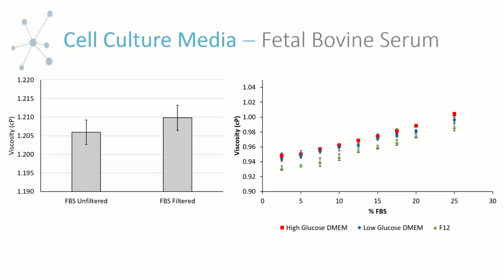And then we wanted to see how the combination of FBS and different mammalian medias, how does FBS influence their viscosity, since FBS is a little bit higher viscosity than the standard DMEM or F12 media. And as expected, as you increase the concentration of fetal bovine serum in the formulation, the viscosity increased accordingly. And we varied the concentration from 2.5% all the way up to 25% FBS, which covers basically the entire range of experiments and formulations that I've seen in the literature for supplementing your media with FBS.